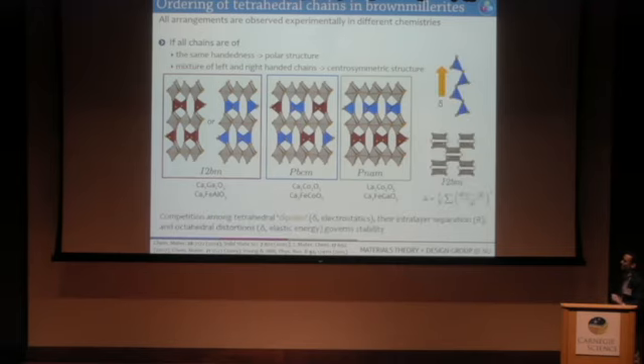Okay. And so in the literature, there's quite a bit of discussion about what types of chemistries favor particular space groups. We looked at this a few years ago in an electronic structure study, and ultimately it's a competition between the electrostatic interactions among these dipoles and an elastic energy that happens when these tetrahedral chains rotate. So the linkage along this direction is through an apical anion like this. As these tetrahedral chains rotate, unlike perovskite, they shear the octahedral layers. They don't keep a rigid octahedral unit, and that costs elastic energy. And so ultimately the competition among these types of interactions is what governs the stability. So I don't have time to go into too many details about the stability, but it's in this series of papers here.